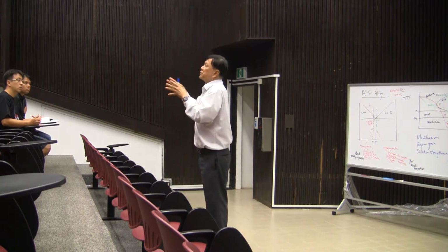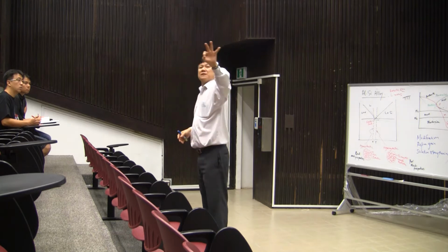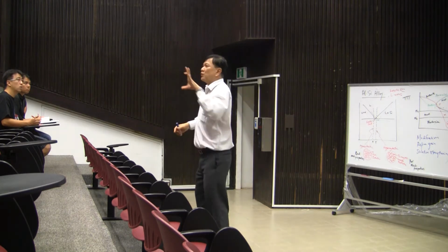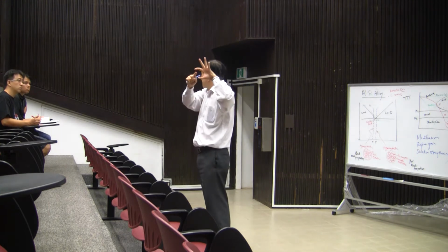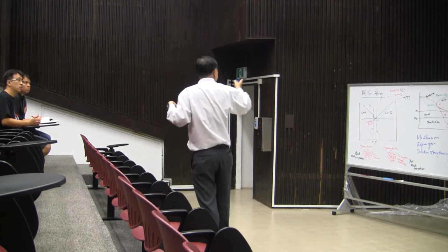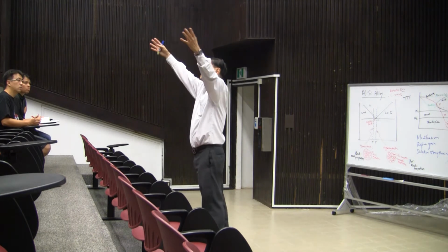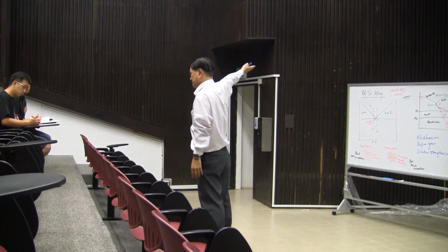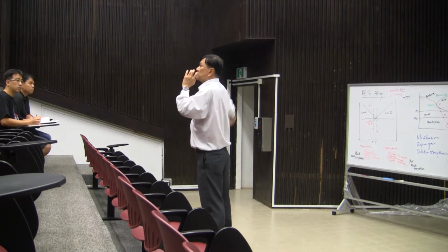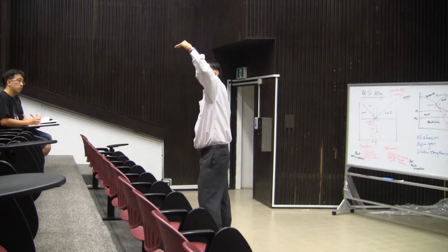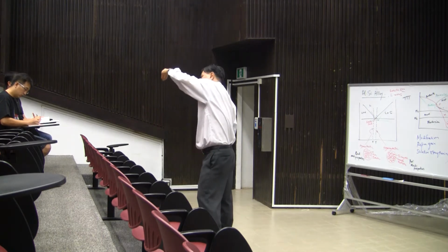But if you keep on doing it, it will grow and grow until eventually it will start to form its what? Grain boundary. It becomes what? Independent. Once it becomes independent, you lose the distortion. Are you clear now? So it becomes what? Over-aged. That's why your strength will start to drop.